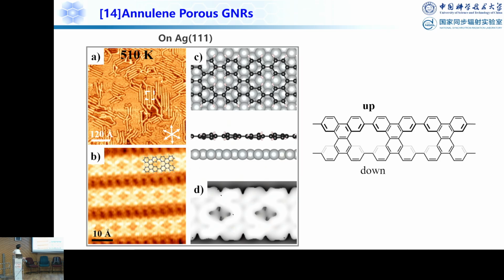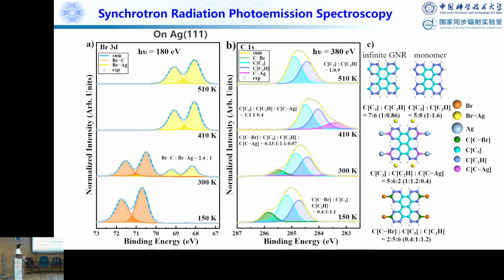And then if you go further to 510 Kelvin, now you form the porous graphene nanoribbons, and you can see the bright protrusion on one side and the dark on the other side. This is due to the nonplanar structure because you have this hydrogen repulsion in between, so this side goes up and this side goes down. This is the DFT calculated result, which is consistent with what we observed. And now the synchrotron radiation photoemission can really help to understand the reaction mechanism.